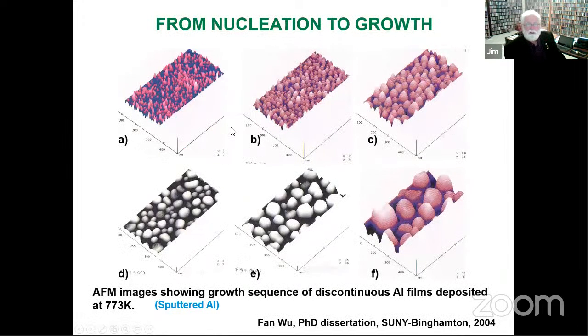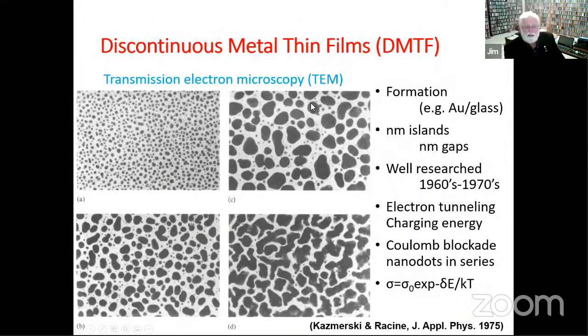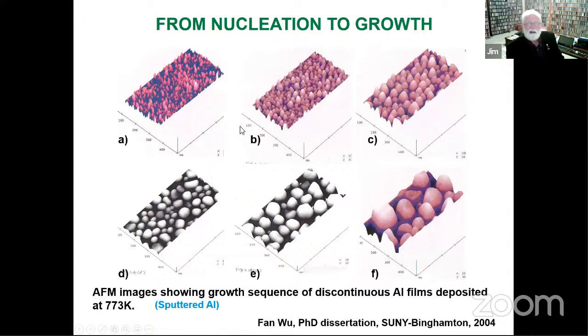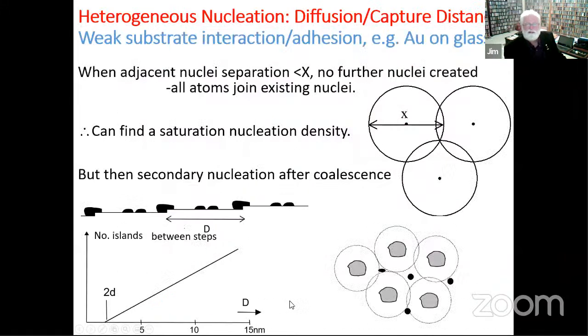This is showing the same sort of thing, but now instead of transmission electron microscopy, this is now in an AFM. You can see small islands growing together, and the point here is that this is sputtered aluminum. And as far as I know, this is the only study using sputtered films or aluminum films at very high temperature. I put this in just for extra interest.